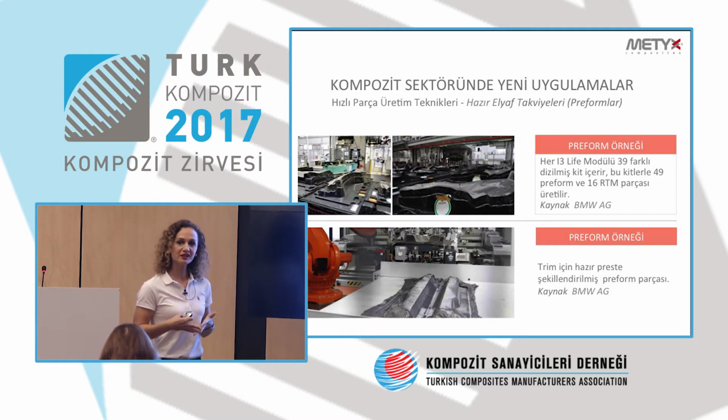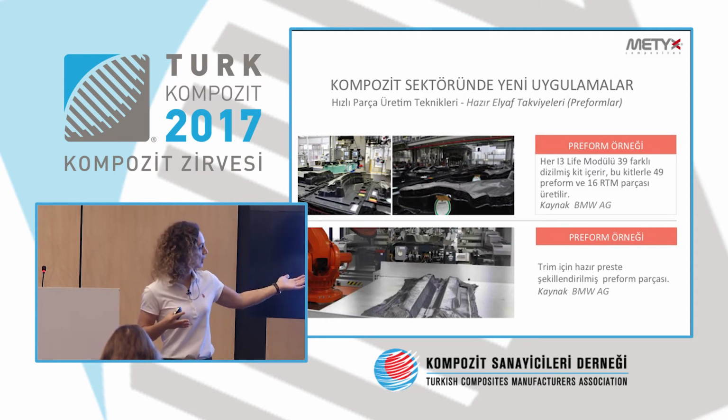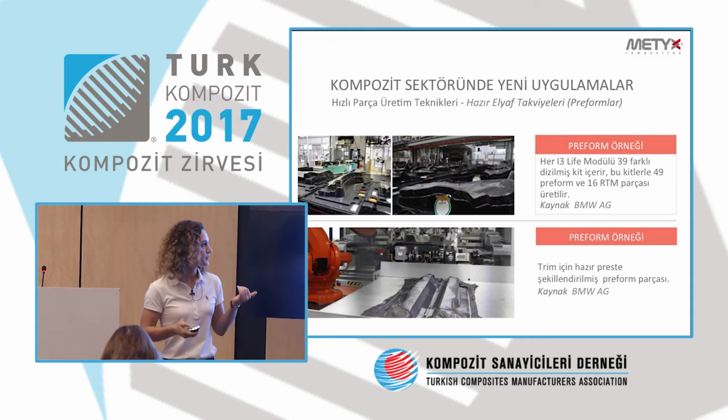Another parameter for us is the preforms. The fabrics. Think about an RTM mold. You would like to make a production, and your pieces have a great shape, but you are going to cut the fabrics, and it is going to take a lot of your time. The aim here is to save time. So what are we doing here? Carbon fiber has been used here, and they are all put over one another and pressed. So the materials are formed, and you put it into your mold. You close the mold and put the resin inside it. You make the resin flow inside it, and you receive a piece.